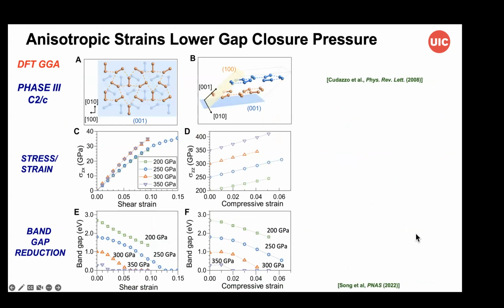This is also quite relevant to some work that was done in collaboration with Jiangbin Chen's group, as well as Yanming Ma's group, on the effect of anisotropic strains. And this actually can help resolve some of the controversies in terms of where the pressure onset is in this material for the metallization or for band gap closure. What we found in these calculations that were just published is that, in fact, there is significant strength in these materials at high pressure, as shown here in these plots in the middle, the shear strain and compressive strain that's supported in these diamond cell experiments as modeled in these DFT calculations. And this anisotropic strain can lower the effective pressure of the onset of metallization in the system, as shown in the bottom plots for shear strain and anisotropic compressive strain.